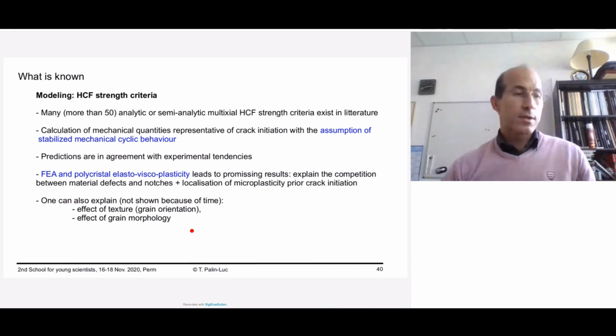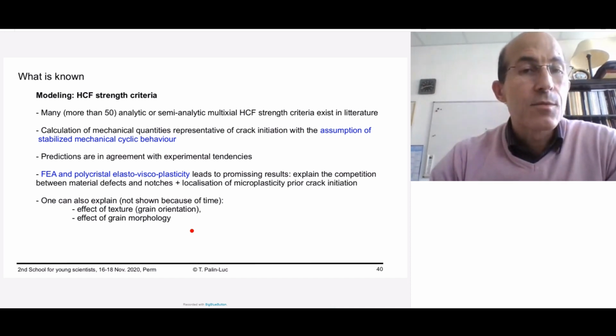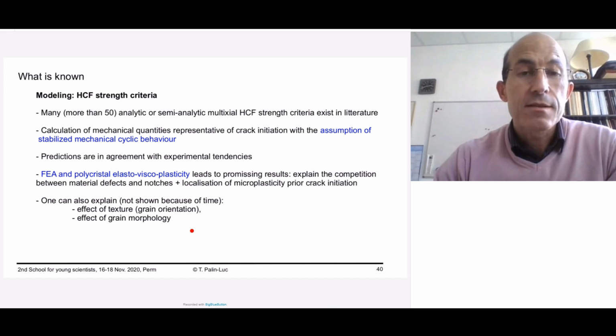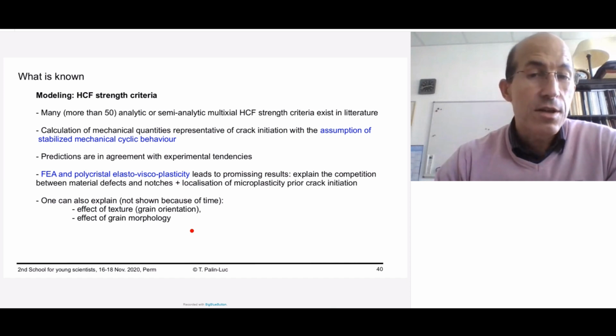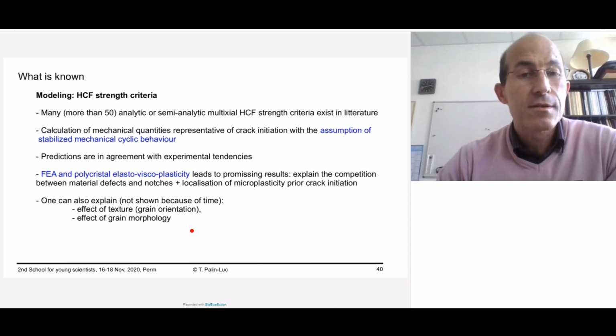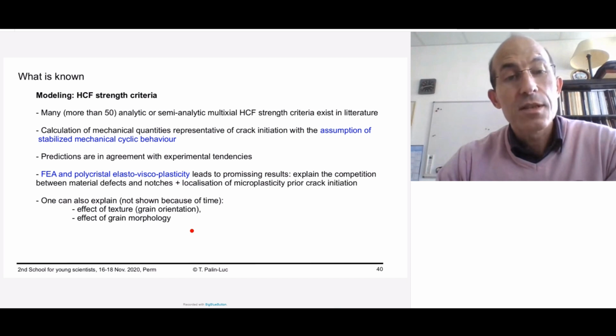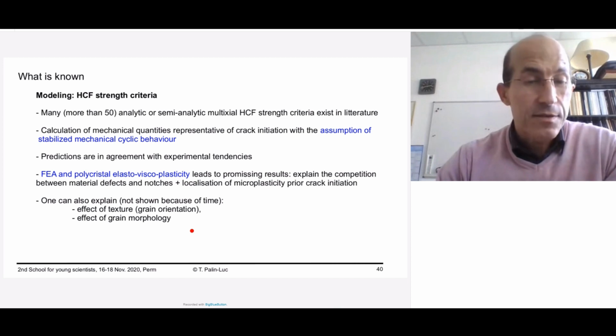So, as a conclusion of what is known, we can say that modeling high cycle fatigue with the strength criteria is mainly done in literature with analytic or semi-analytical models. The calculations of quantities representing crack initiation are done with an important assumption, that the material must be stabilized cyclically speaking. This is important because in the criteria you compute everything on a single load cycle, and you assume that your quantity will not change if the loading is reproduced or repeated maybe 1 million or more cycles. I do not have enough time to show you, but the predictions are in agreement with many experimental data.